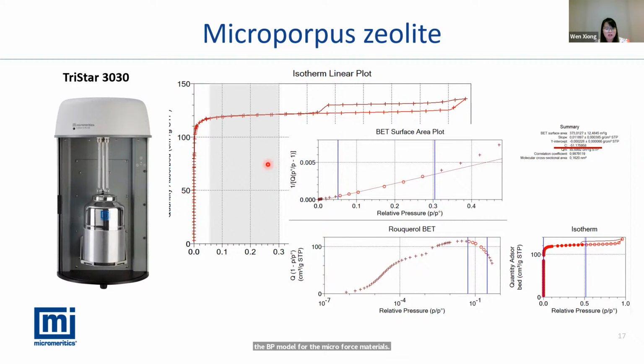Firstly, when we do the BET data reduction for the microporous zeolite materials here, we get a C value. If you are able to see here, it's a very large negative number. As I explained earlier, we are not allowed to rely on the data or the report when we get a negative C value. So this means the classical BET range, like we mentioned earlier, the relative pressure from 0.05 to 0.3, is not sufficient for the microporous materials. We have to figure out how we can do that.